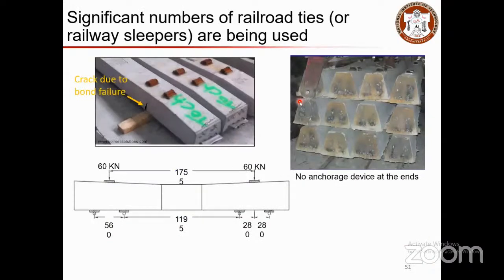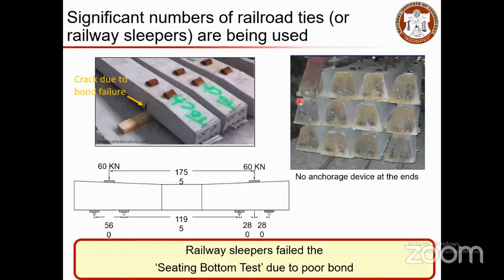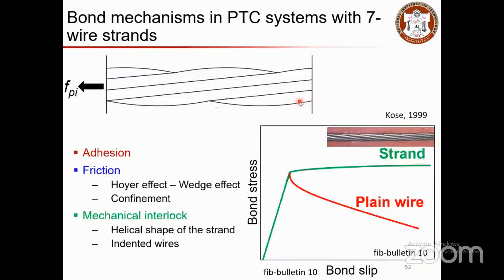The only difference is that the diameter of the strand used in railway ties will be lesser than the one used in bridge decks and buildings. And even here in railroad ties, we have observed a lot of issues, seating bottom test failures due to poor bond performance. What we observed is that the bond mechanism in pre-tension concrete systems is mainly governed by adhesion, friction, and mechanical interlock. And when you talk about strands, the mechanical interlock plays a major role.